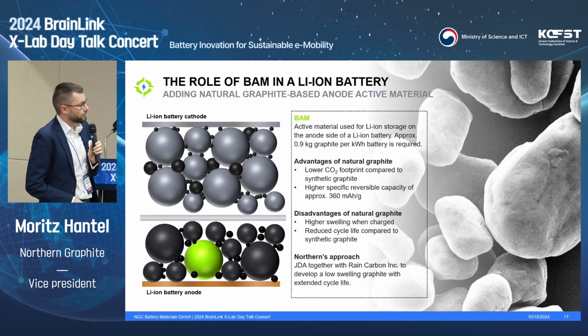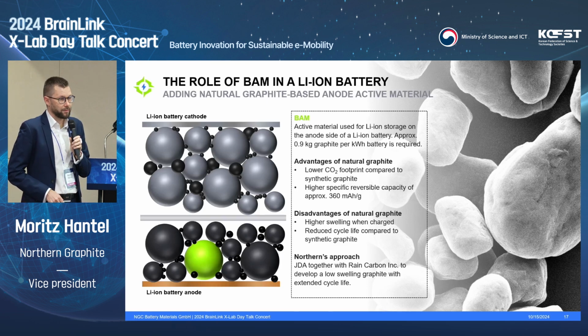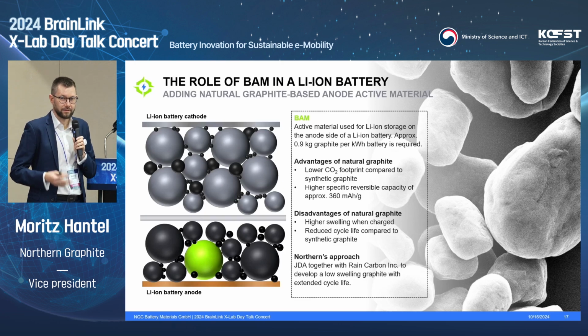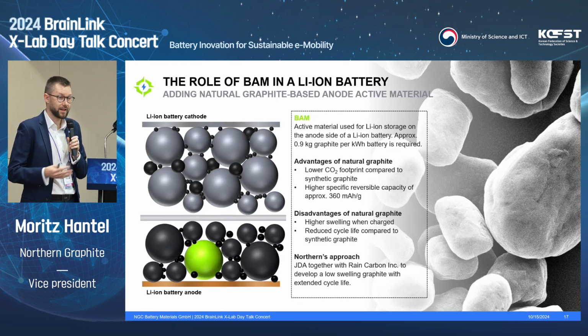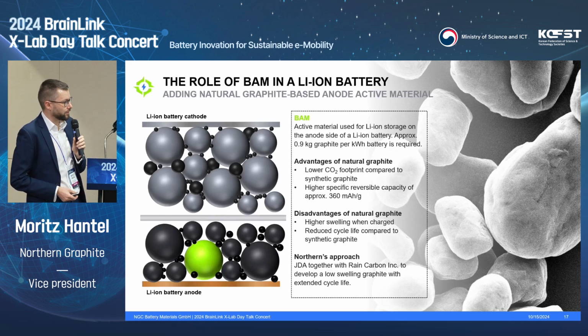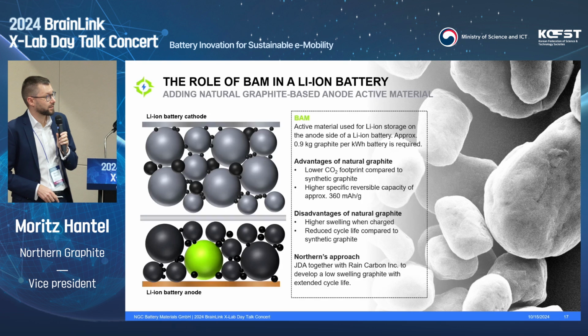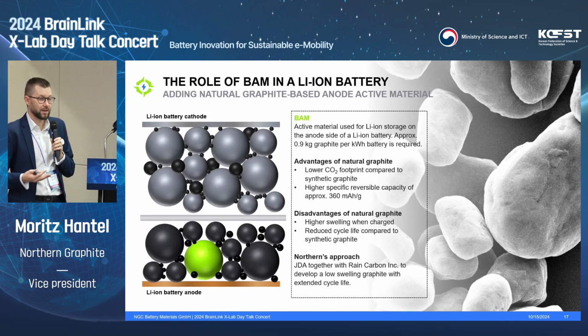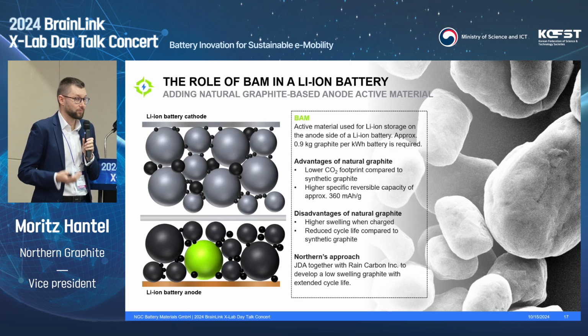To give a little bit of perspective, typically the graphite can be used on the anode side, and in reality it's never a pure natural graphite-based material. So typically a blend is used where still around 50–60% is coming from synthetic graphite and another 30 to 50% from the natural side to reduce, and that's I think the advantage of natural graphite, the CO2 footprint. So also bringing the CO2 footprint of the battery down. We have the advantage of a higher specific capacity, which for natural graphite is around 360 milliamp hours per gram. Synthetic graphite ranges to 340, 350, so it's slightly lower. Disadvantages are typically higher swelling and slightly reduced cycle life.